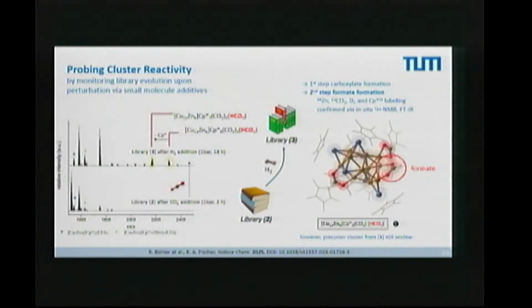We can use first CO2 addition and then hydrogen addition. Now this one, this mass spec is the one we create when we have the library generated, wait a little bit, and then add the CO2, wait a little bit, and then add the hydrogen. Now look at this situation here. There is nothing, and there are two peaks after we add the hydrogen. This one is a molecular ion, this one is a fragment, and the difference is kicking away 1 Cp star. So this one is new, and this reads in that way.